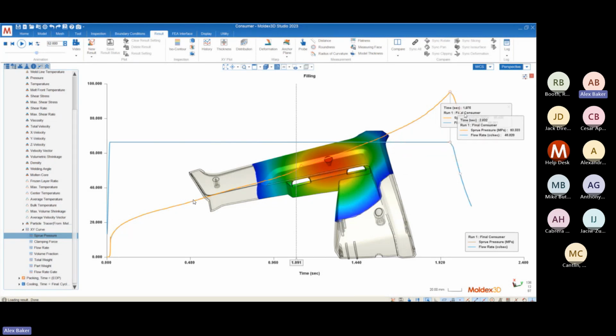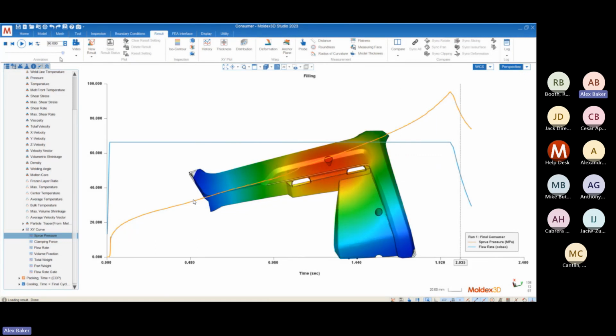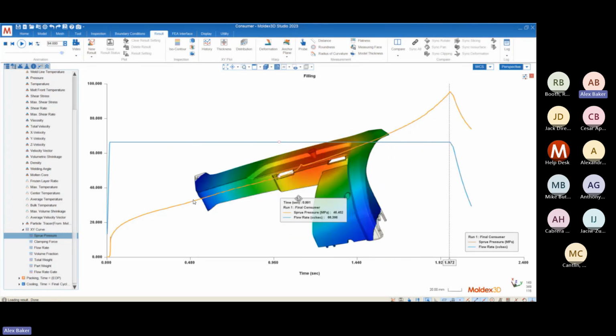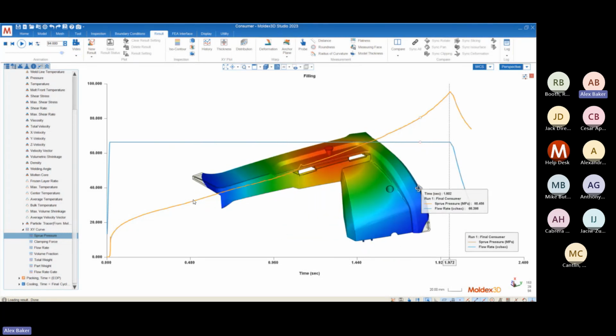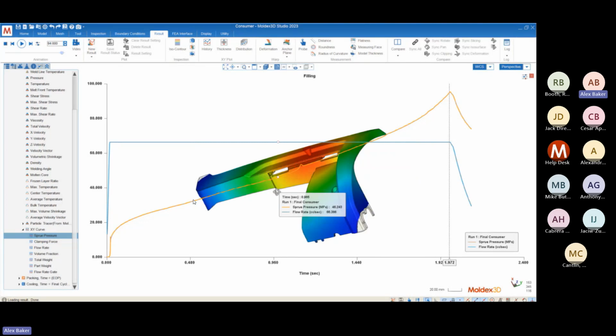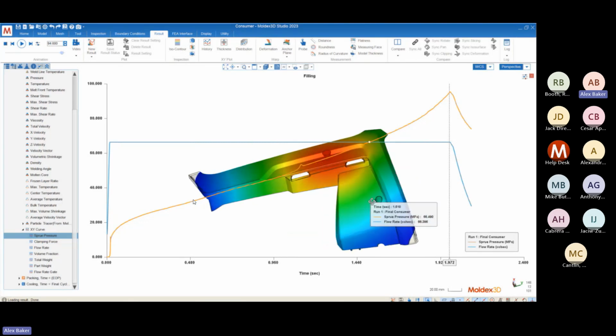All right, so while 95% is a good rule of thumb, I usually use the VP switch point, which is actually the maximum value here more times than not. I usually use the maximum value as the true balance point that I need to study. In this case, 94% instead of 95. Sometimes it'll be later, sometimes it'll be earlier.